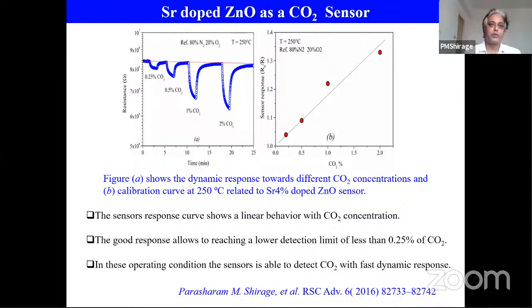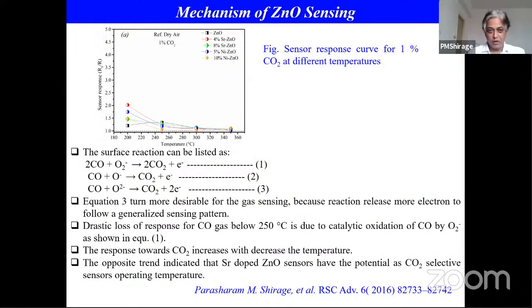Okay, then if we dope zinc oxide with strontium, then this will be a good CO2 sensor. Again I measured the resistance, and with different concentrations of CO2 we plotted the calibration curve. By using this calibration curve, the minimum amount of CO2 we can detect is 0.25% of the CO2 present in the atmosphere. So nickel doped zinc oxide is good for a CO sensor, and strontium doped zinc oxide is good for a CO2 sensor. Okay, and what is the mechanism?